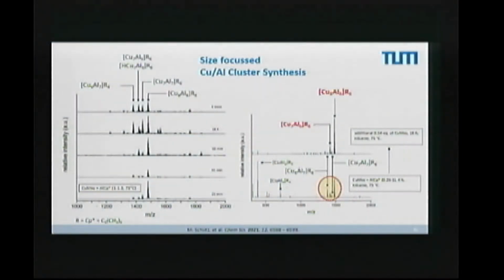So even in the best case, when we narrow down the selectivity, we call it size focusing of our synthesis, we may have a dominant cluster, maybe that's 90%. So on the crystallographic position of this cluster, 90% is occupied by, let's say, copper 8 aluminum 6, but the other 10% might be occupied by the hydrogen copper 7 aluminum 6, and you cannot get rid of that. It's an intrinsic problem of the dispersion which we intentionally create.